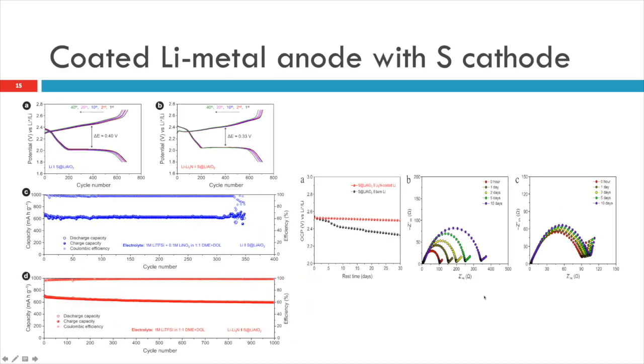So then we started using that lithium metal foil, which is covered by the lithium nitrate, against the sulfur. And we see that there is a significant difference in the polarization. Obviously, it shows very minimal polarization. Cycle life also improved. And here, if you have not modified it, then you can see the disturbance, and then the cell actually failed. We have done several other things, but for time we may not discuss them.